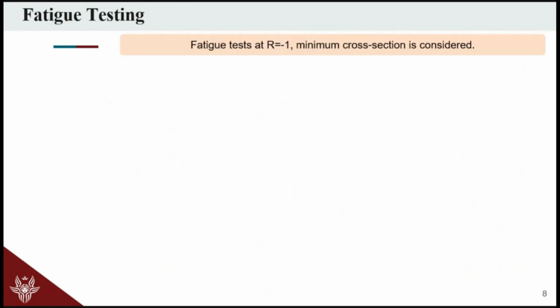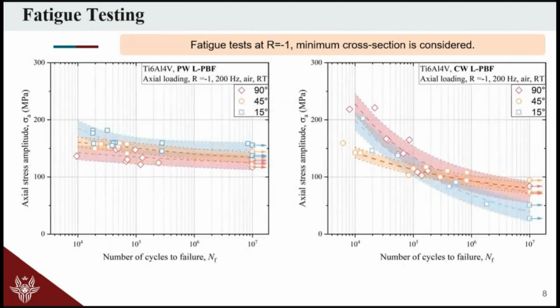As I said and anticipated, we are using the minimum cross-section for our data analysis on fatigue, and in particular, fatigue tests have been done at R equal to -1 in mode 1, and these are the S-N curves, Wöhler curves, of the components for the pulsed wave and the continuous wave according to the 3 different building orientations. Why the choice of the minimum cross-section? Because in this way, we can already account for the differences that we have in terms of morphology, at least in a preliminary stage. If we had used the nominal cross-section, we would have way larger discrepancies, which would not have accounted for this difference.